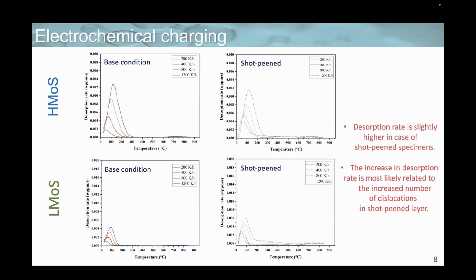So on this slide, you can see the results of electrochemical charging coupled with thermal desorption spectroscopy. On the left side are the results for the material in the base condition, and on the right side for the material in a shot peened condition. If we take a look at the results for the high molybdenum steel, we can see that the desorption curves appear to be mostly similar. There is only a slight increase in desorption rate. And for the low molybdenum steel, the situation is similar. However, the increase is a little bit more pronounced. This increase in desorption rate is most likely related to the increased number of dislocations in a shot peened layer.